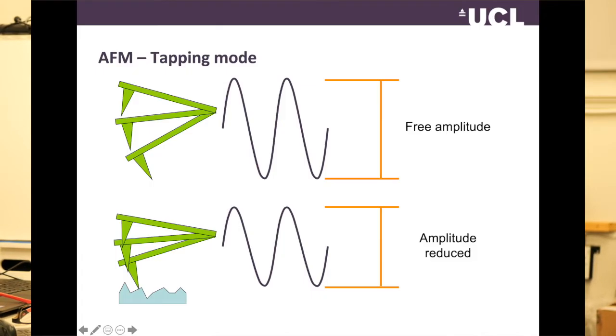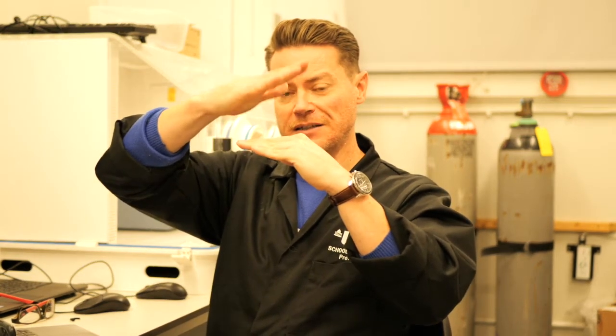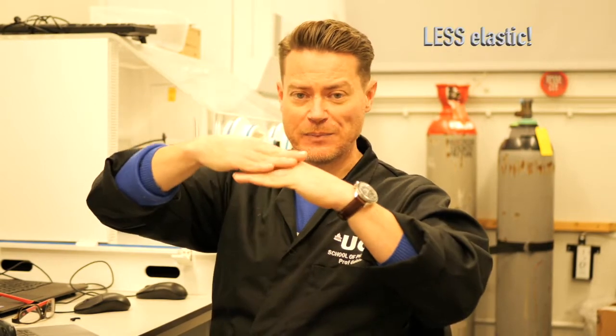Just one thing to note here, it is possible to make these measurements in a slightly different way by tapping. So imagine that your material is very hard. You can bring the tip down and you can bounce the tip up and down off the surface of this material. And if this is a truly elastic solid, then the tip will always bounce back to where it started. But if it was a less elastic solid and you bounce, then it becomes damped because the material is starting to absorb the energy from the tip.